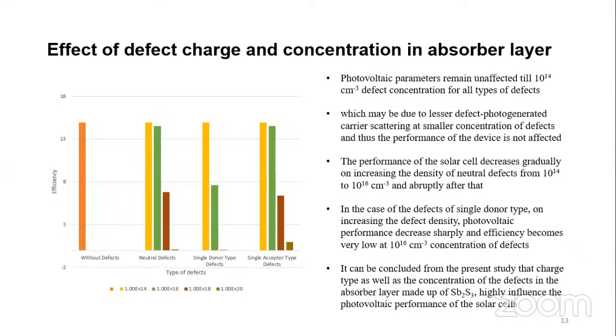But as we move forward with higher concentration of defects, the performance of the solar cell decreases. In the case of neutral defects, we see that the performance degrades gradually on increasing the concentration from 10^14 to 10^16 per cubic centimeter, and abruptly after that. In the case of defects of single donor type, we can see that on increasing the defect density, the photovoltaic performance decreases sharply and efficiency becomes very low at 10^16 per cubic centimeter concentration of defects. So we have concluded from this study that the charge type of the defects as well as concentration play a significant role in influencing the photovoltaic performance of the solar cells.